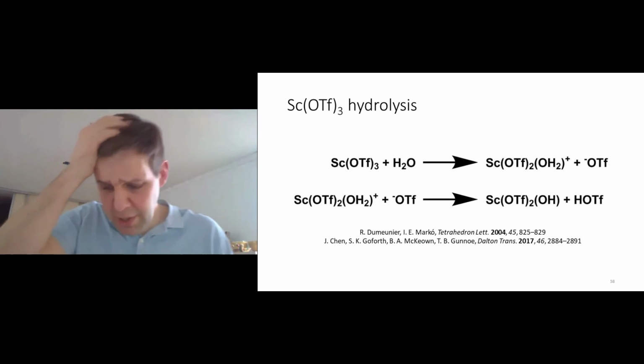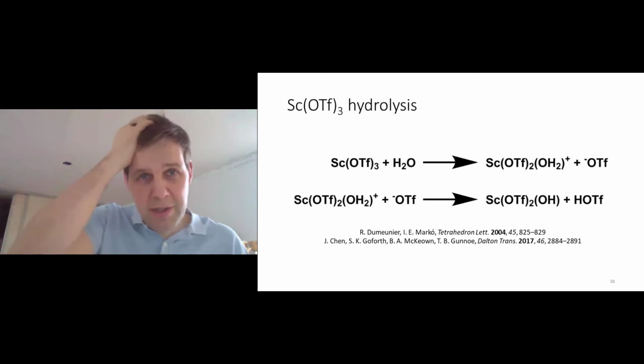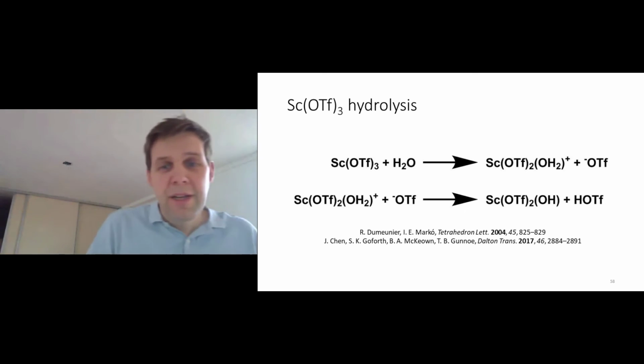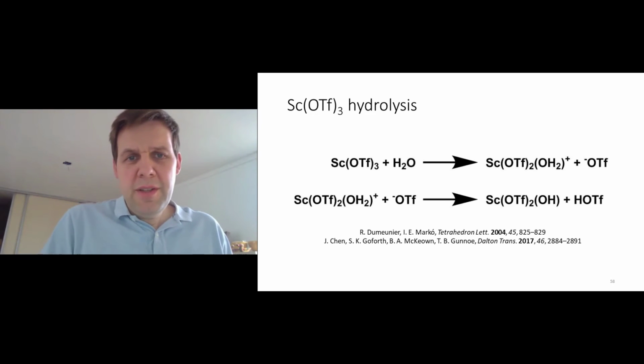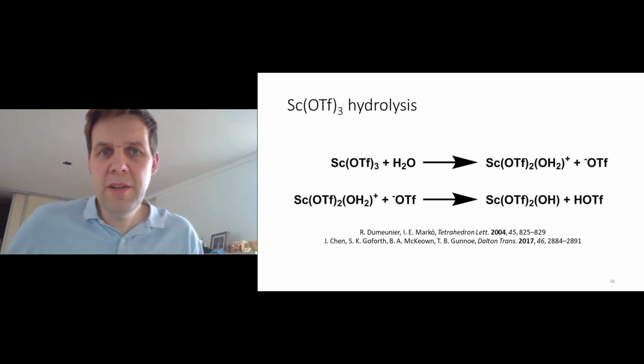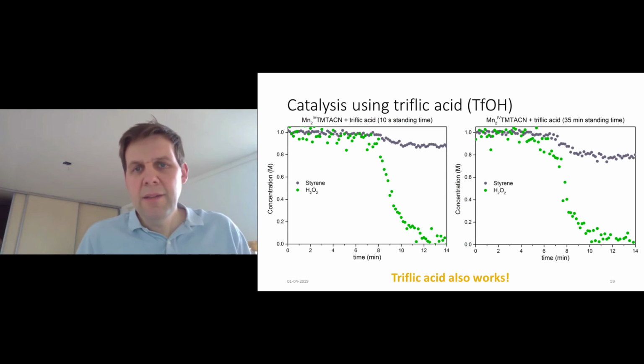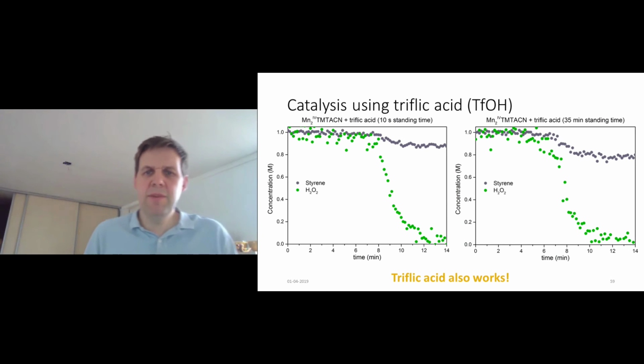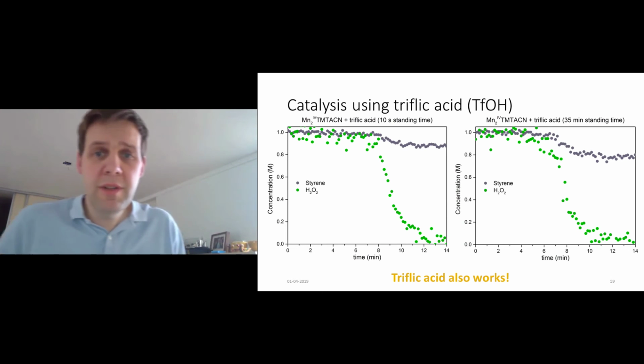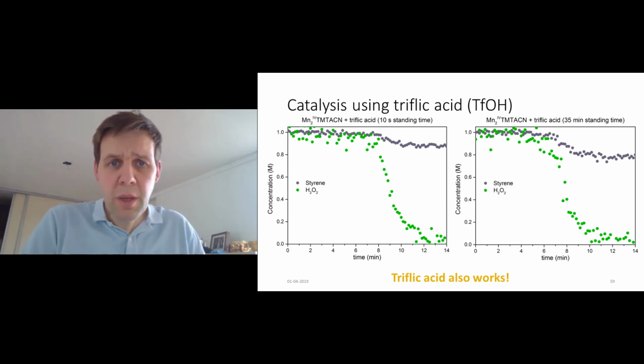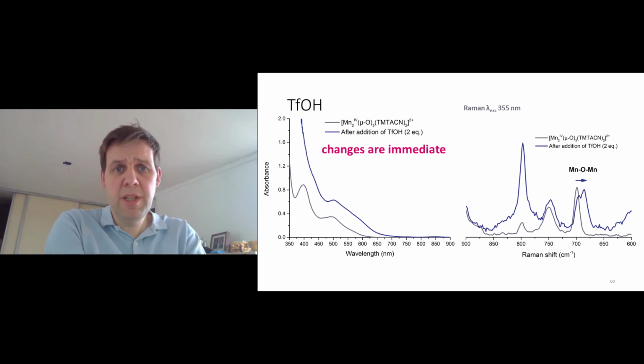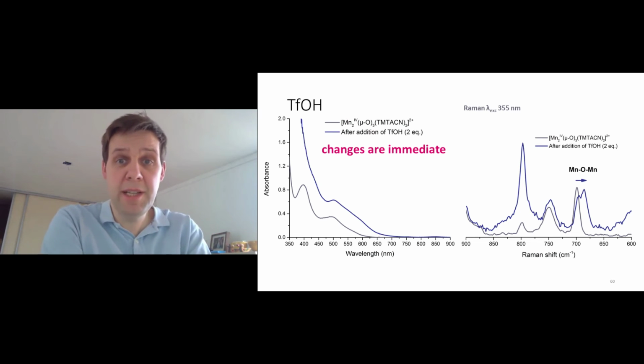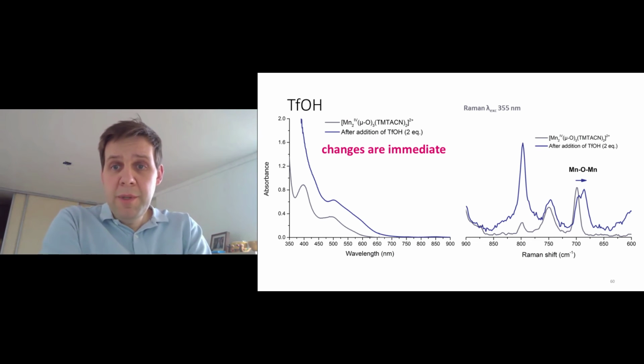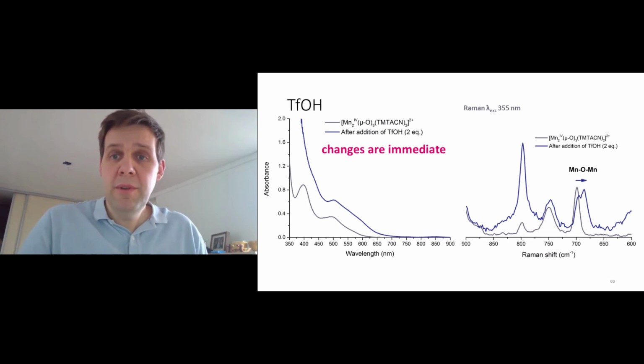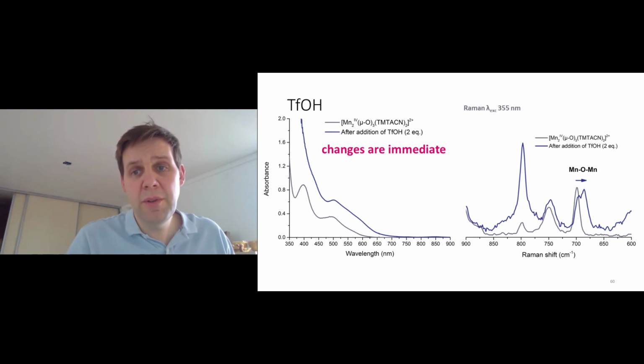Now, it's a good thing to read the literature. We always say in the group, 2 hours in the library saves you 2 weeks in the lab. If you read the literature, you see the scandium triflates are prone to hydrolysis to release triflic acid. That's an easy one. So we add triflic acid instead of scandium, and we see more or less the same behavior that we see with scandium. Triflic acid also works, and triflic acid is a Brønsted acid. More than that, if we look at the absorption spectrum, we see that the changes are not over 80 seconds, they happen immediately. And if we look at the Raman spectrum, we get the same changes that we get with scandium, but it actually matches what we calculate for protonation.